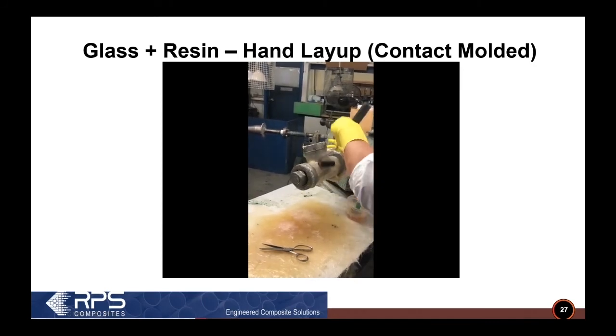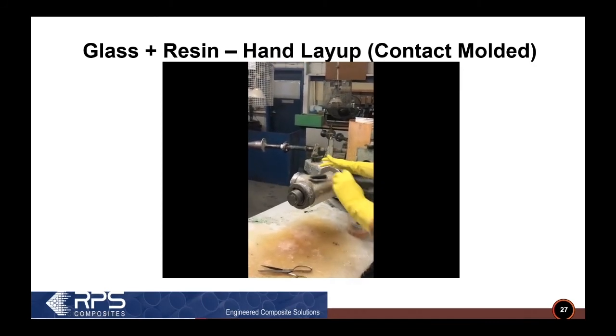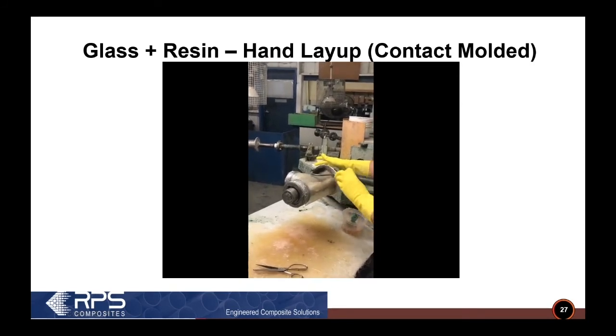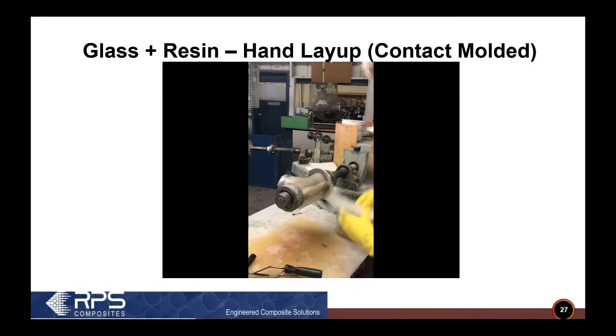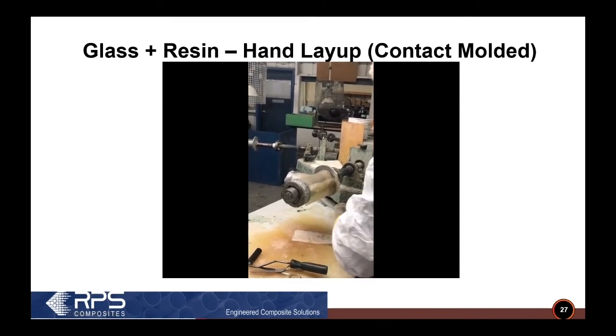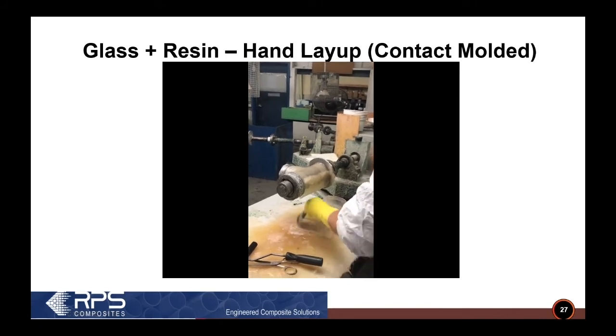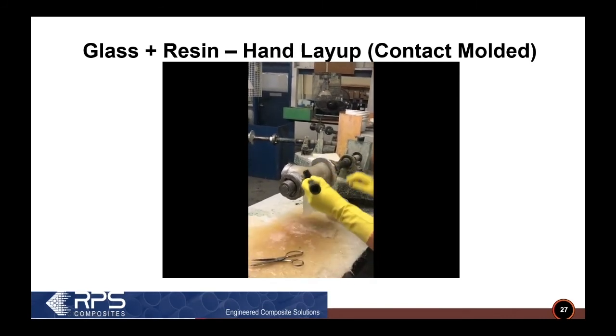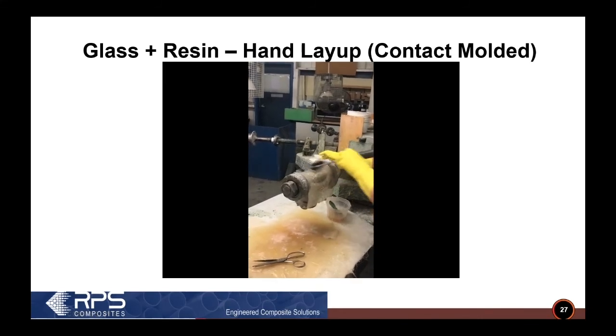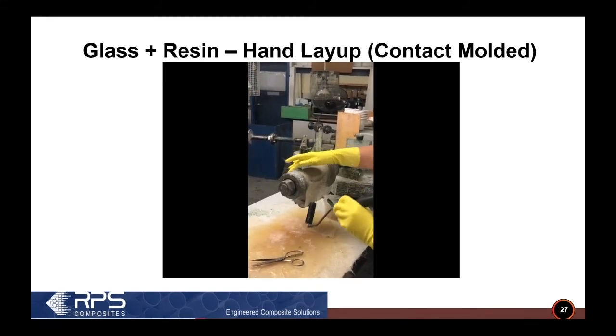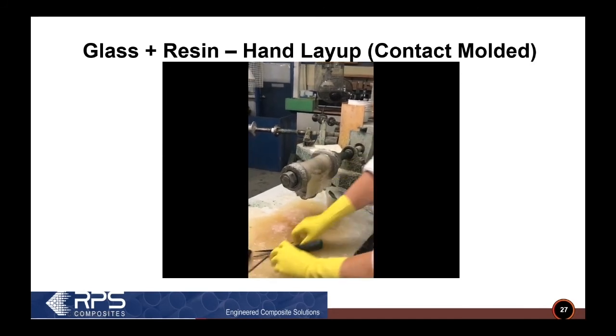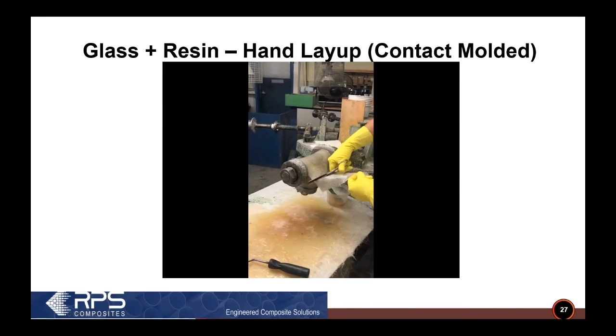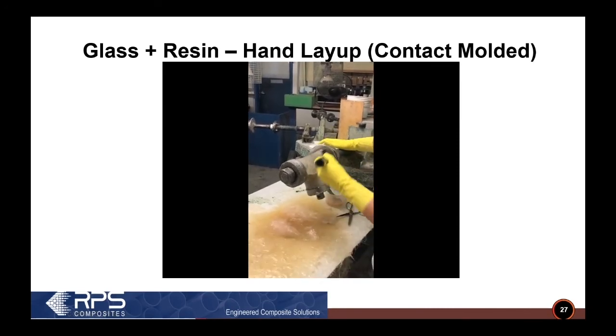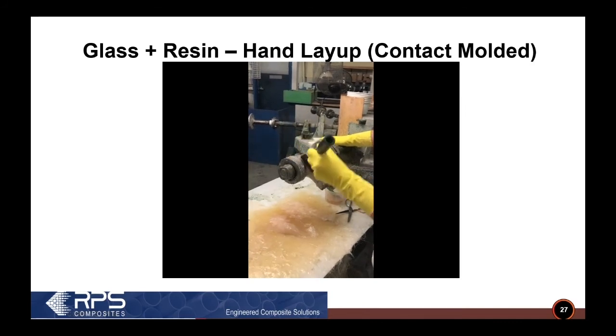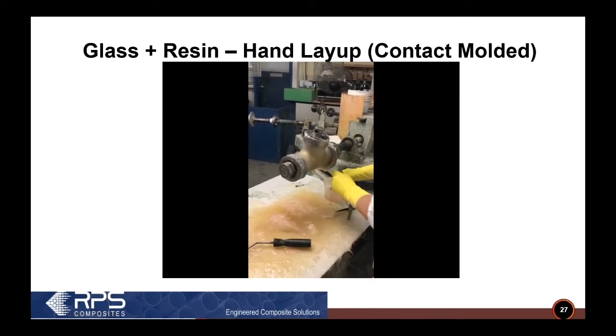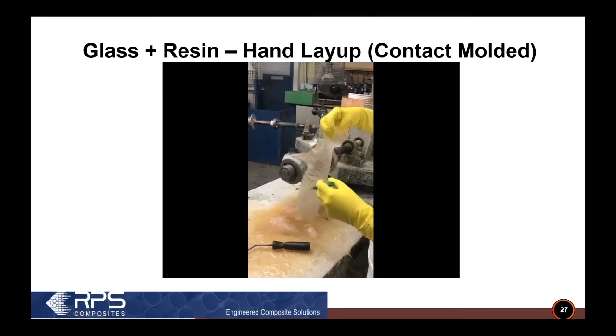The laminate is going to be full of air when you apply it to the mold, whether it's a butt joint that you're doing in the field or making a fitting here in the shop. So the laminator, the technician, rolls out all that air, and here you can see them applying a second layer of reinforcement. It's actually the top piece of the tee in this case. They've saturated that second layer of reinforcement. They're just going to finish rolling out the air from the first layer. I think she actually cuts a little bit off here because the glass kit that was pre-kitted was a little long in this case. She rolls it out, and then she's going to take that other layer, which goes around the top of the tee, and repeats the process.